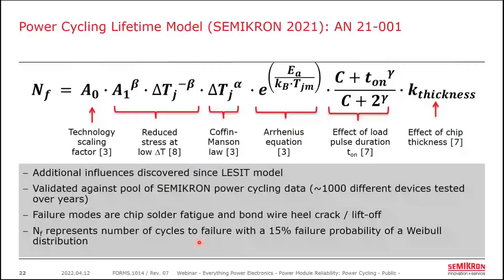Well, again, I guess that goes back to the topic we just discussed. The model is valid for 60 seconds, and it's valid for these failure modes here, like I said, chip solder fatigue and bond wire failure. For longer temperature cycles or longer heating times, that's when you really start to get into base plate degradation and things like that. And right now, there's not that many accurate models out there. We don't have a model for long times like that.